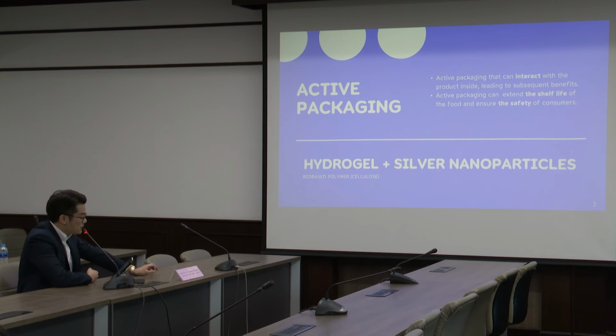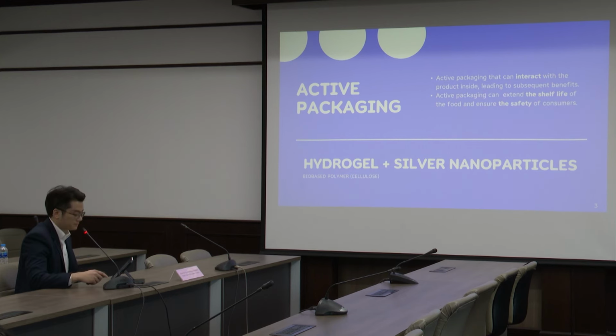In this study, we utilize the hydrogel, which is commonly found in meat packaging and serves the purpose of absorbing the meat exudate. Moreover, we modify the hydrogel to release an antimicrobial agent. In this research, we use silver nanoparticles. Taking into consideration environmental sustainability concerns, to achieve this, we replace the petrochemical-based polymer with a biodegradable polysaccharide, namely cellulose, to produce the hydrogel.